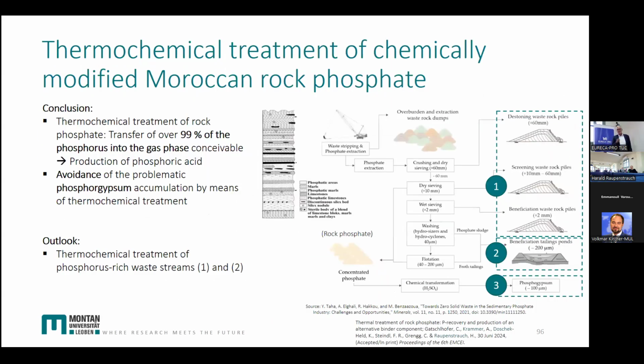So, what is the conclusion of our first experiments? We could transfer 99% of the phosphorus into the gas phase. And that's much, much better than the traditional wet process, which is quite nice. And we could avoid phosphogypsum, which is important as well.